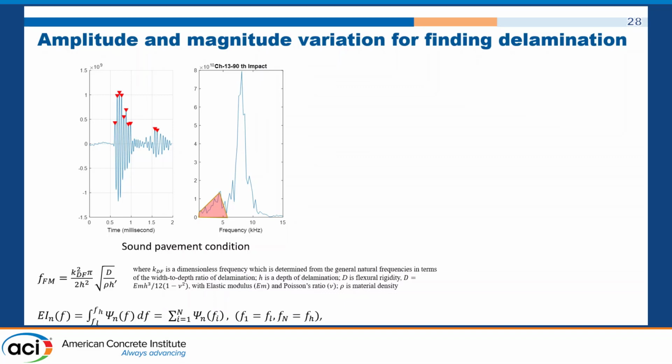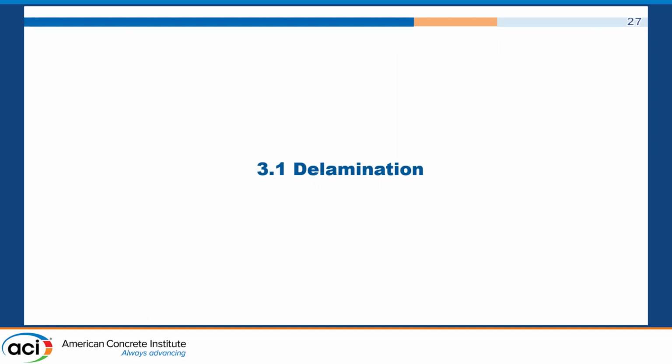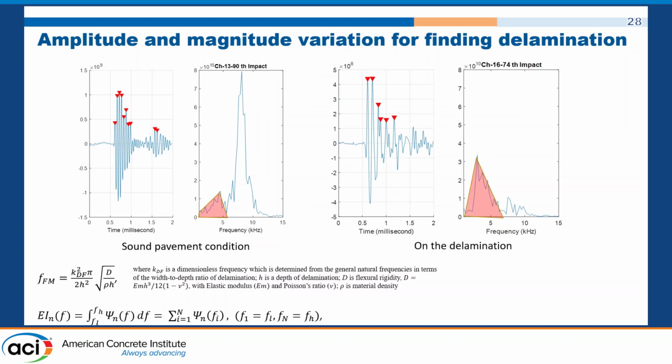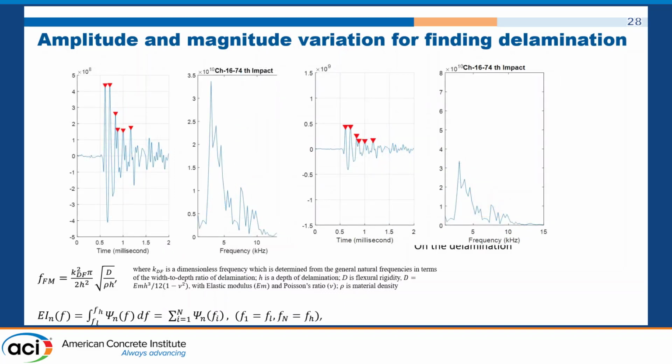It's okay. So we have 3 different types of deterioration we're looking for: one is delamination, another is surface crack, and the other is corrosion. If you look at delamination, it's based on impact echo. Then we can look at the fracture mode, but in the field we have many different conditions when trying to image the impact data. For example, in this one with 2 delaminations, their energy is different because of the road conditions.